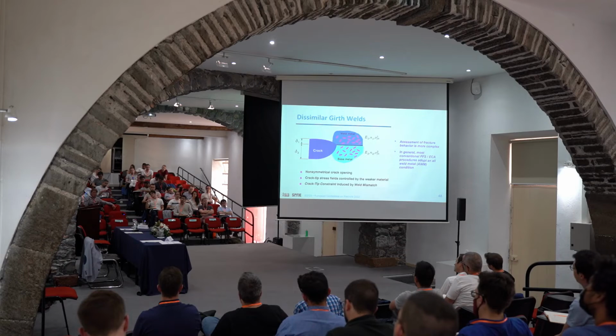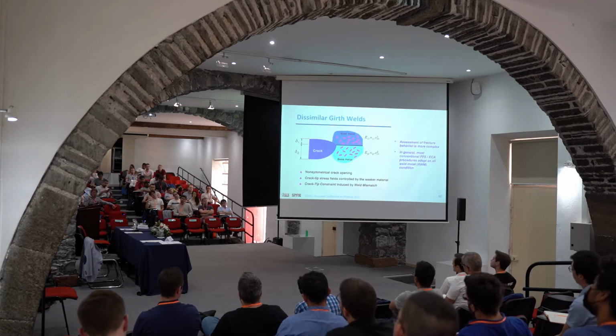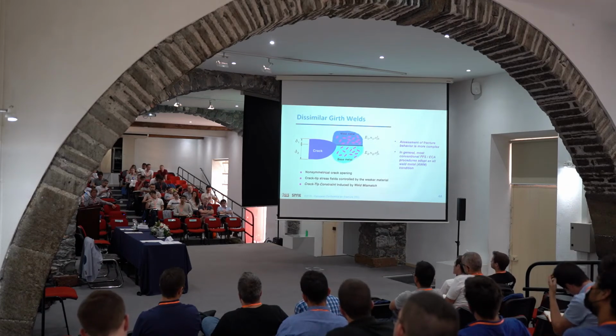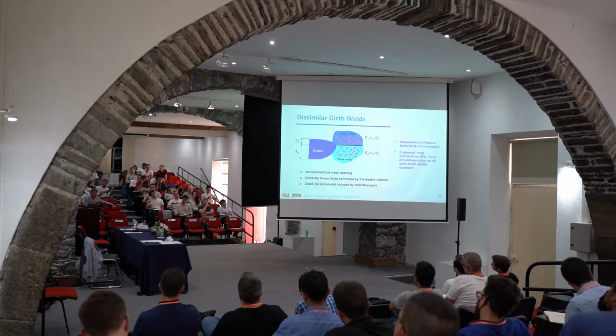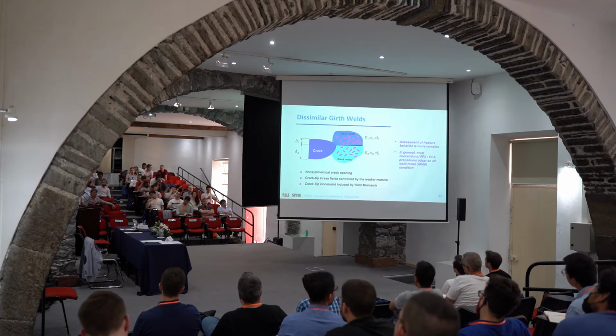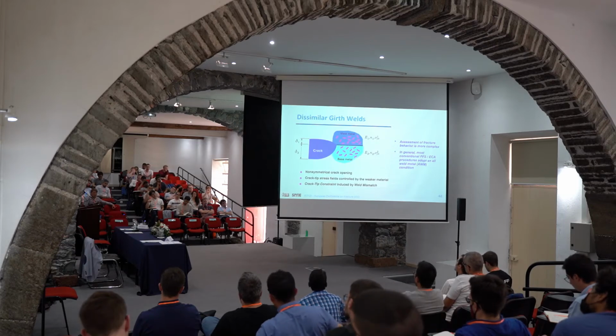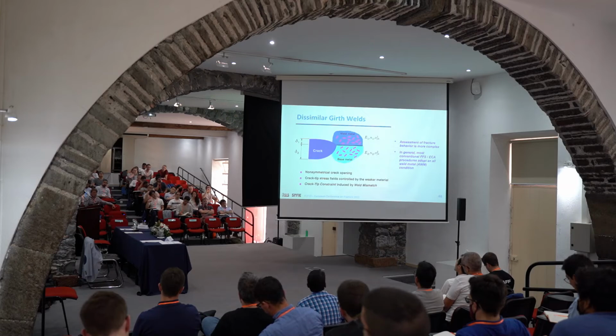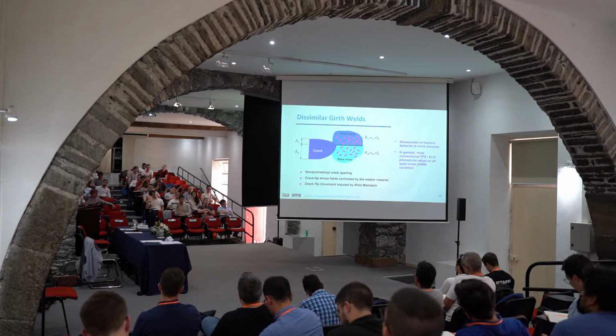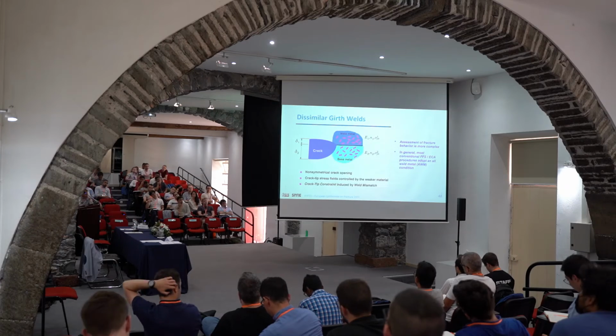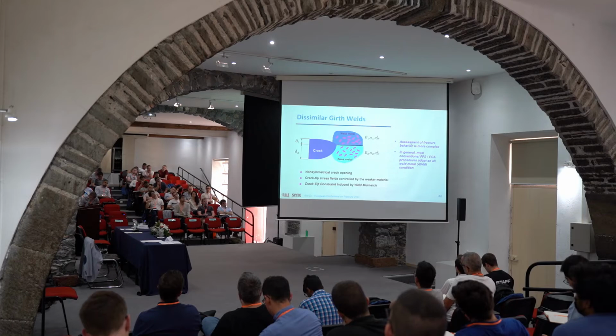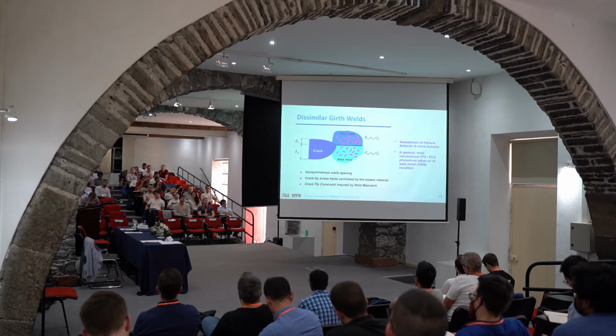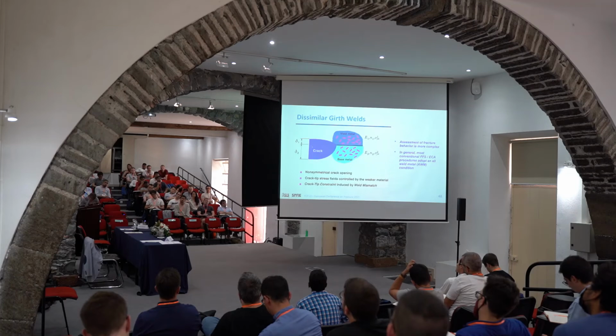Okay? And then you can even relate the CTOD of the J. Okay? But everything is symmetrical. So when you have the similar material, on top of having all those problems that I mentioned before, about the thermal cycle, the microstructure transformation, which is not the same as the base plate material, then we have the asymmetrical opening. Okay? So that makes the assessment of the behavior more complex, because actually we are not sure which CTOD controls fracture. Okay? Is the CTOD in the weaker material, which opens more, or is it the CTOD in the stronger material?